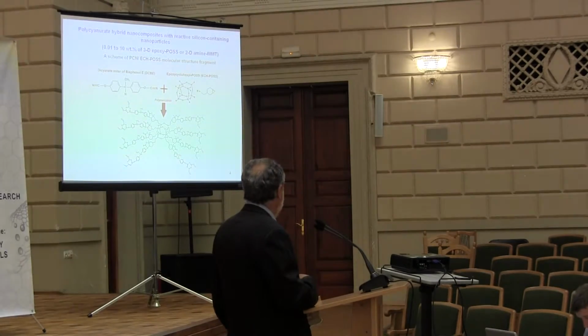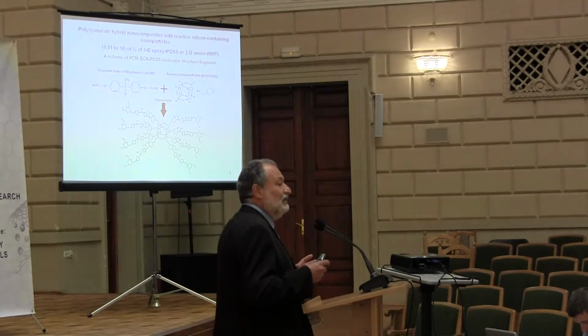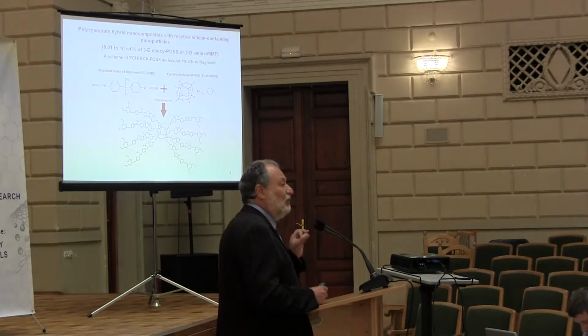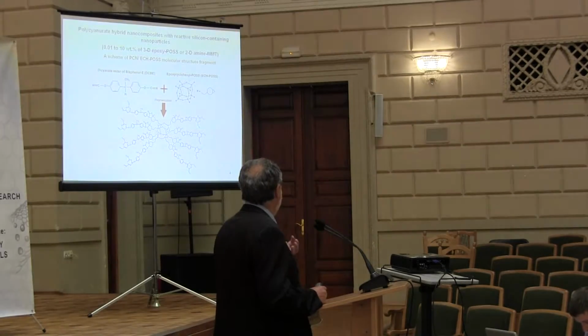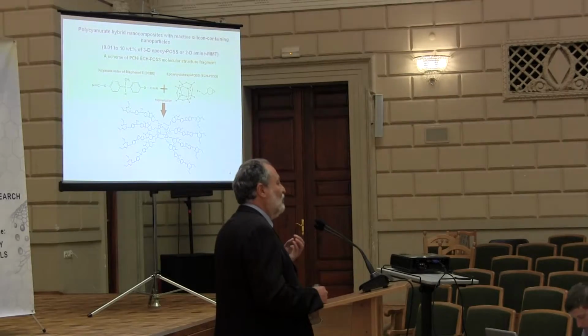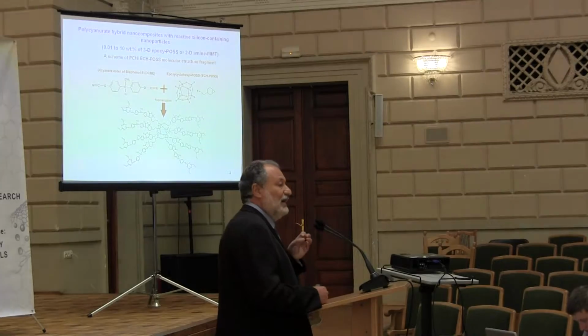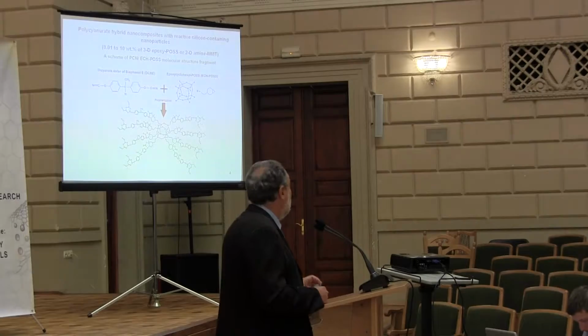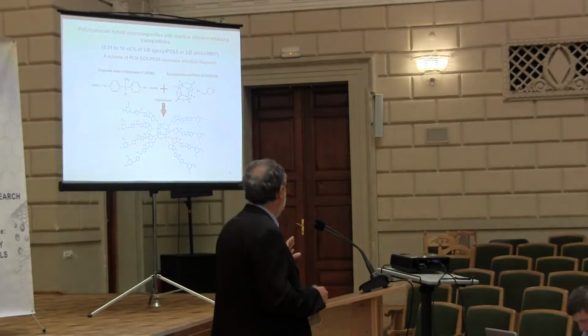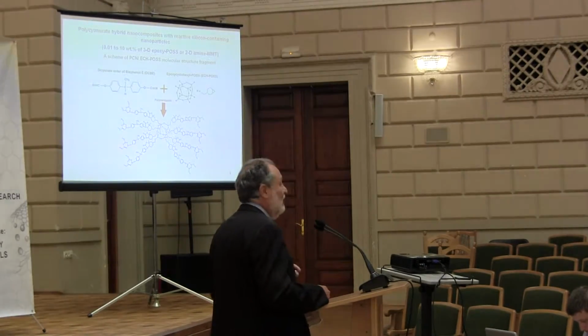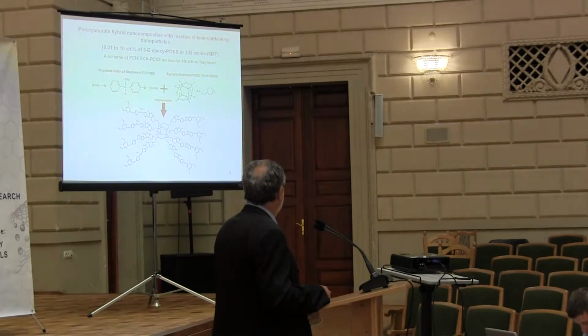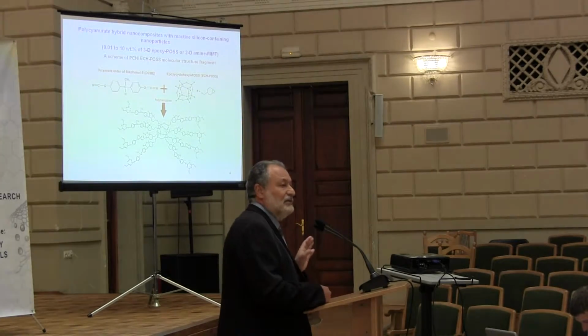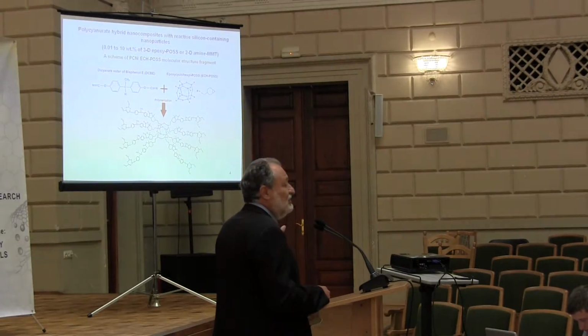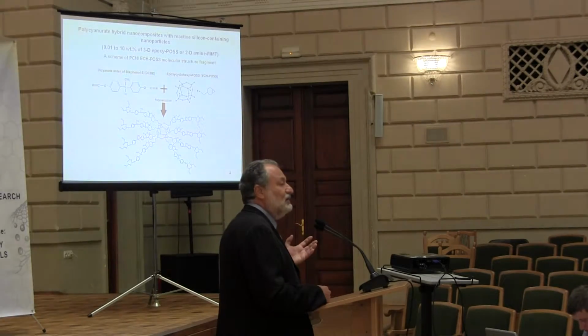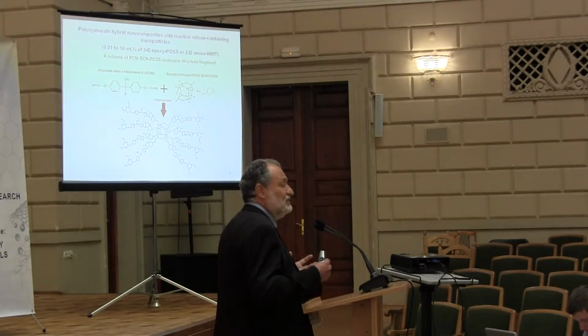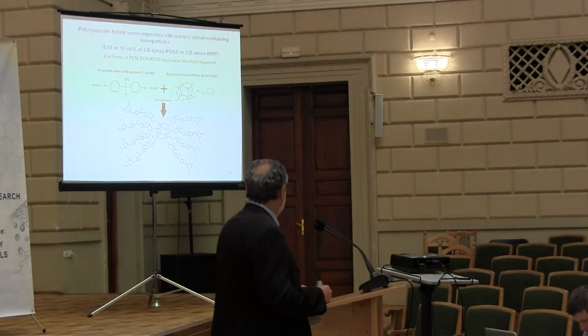And there is a chemical reaction during the network formation. The nanoparticles or POSS of 1 nanometer size are incorporated chemically inside the polymer network. So it improved the dispersing of the nanoparticles due to chemical grafting inside the polymer matrix of each nanoparticle of 1 nanometer size. And similarly, we have the process for obtaining amide monomeramide filled nanocomposites, polysaccharide based nanocomposites. Just a different reaction, but it's a reaction of amine groups of monomeramide with cyanate groups of growing polysaccharide network.